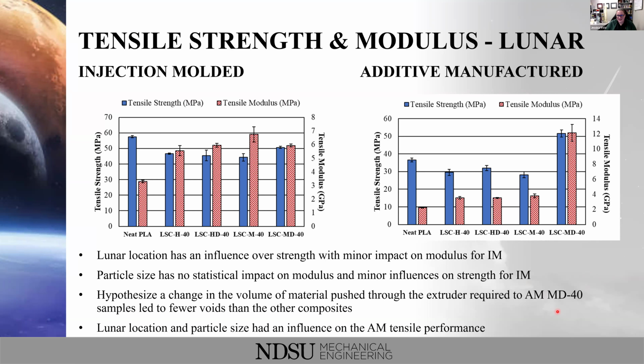This Mare Dust 40 was the one that we had to really increase that E number with to get the material to come out of the extruder and produce a part that didn't have visible voids in it. We were looking for 100% infill. It really increased the properties. These are much higher than what we saw even from injection molding, and certainly much higher than the neat or the other composites. We think what's happening here is that because we increased that E number to get a visibly 100% infilled part, we're actually getting fewer voids within those particular parts.